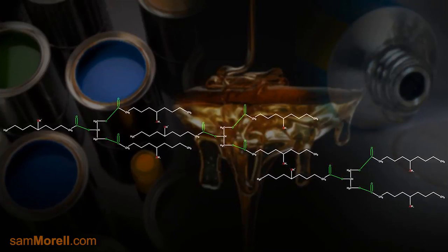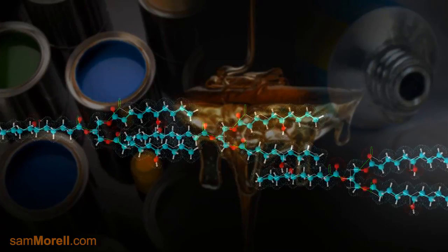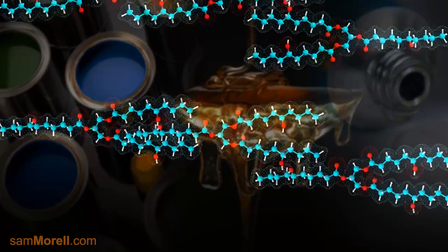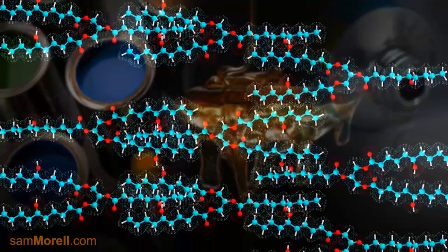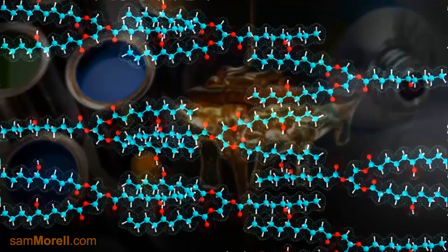Here is a ball and stick representation of the molecules. Notice when these molecules form a network due to hydrogen bonding, we have pockets or voids for pigments, extenders, or other formulation components to nest or be suspended in. And if we were to apply shear, the hydrogen bonding will be temporarily broken, the network collapses, and viscosity is reduced.